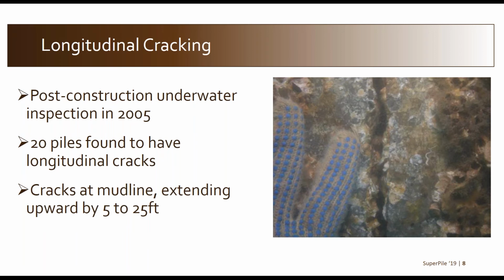It's certainly not a hairline crack, is what I'm trying to point out. And it's probably large enough that the spiral reinforcing steel inside this pile, if not ruptured, then at least yielded and underwent significant plastic deformation. That's the only way a crack this wide could have opened up. So our task was to try and figure out what happened here.